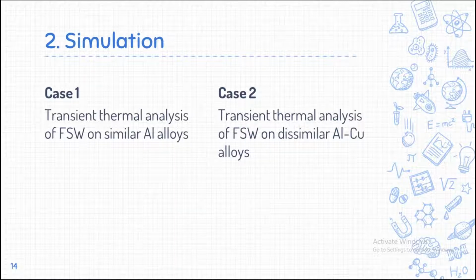75 percent of 660 degrees centigrade is required. Similarly, for different materials, we should have around 75 to 85 percent of the melting temperature as heat input. So using this simulation process, we can vary the parameters. One can play with process parameters like rotation speed, traversing speed, plunging force, etc. Dimensions of the tool can be varied to check which parameter gives around 75 to 80 percent of the melting point of that particular metal to be welded.